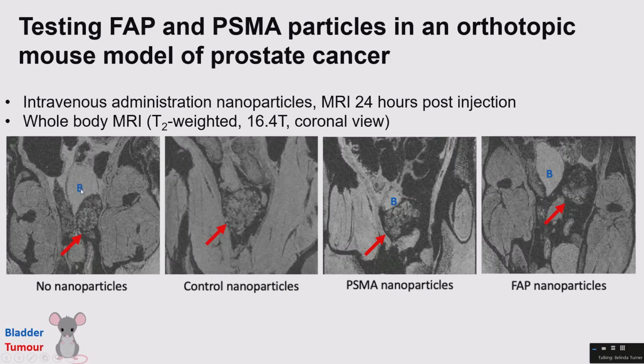So this blue is indicating the bladder, and this red arrow is indicating the tumours in the prostate. On this left side, we've got the no nanoparticle control, which shows the intrinsic tumour appearance on MRI, and then our control nanoparticles that have no targeting ligand. And we do expect some nanoparticles just to accumulate in the tumour through circulation, so there's a small increase in contrast there. But then our gold standard PSMA targeting nanoparticles is a bit more black contrast. That's what we're after in this tumour. But then in the FAP nanoparticles, we were quite surprised to see that these were even darker than the gold standard PSMA, so we're quite excited by this.